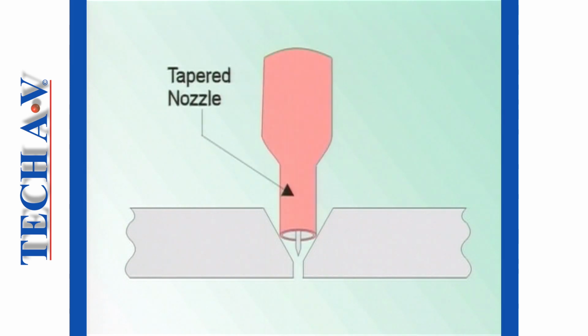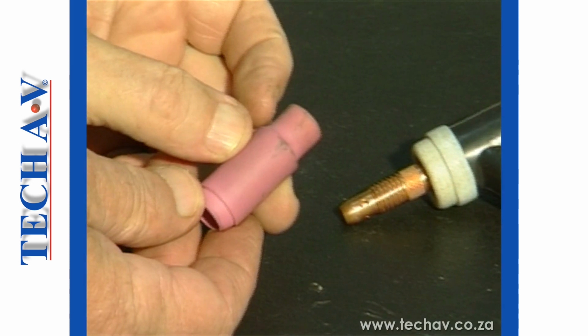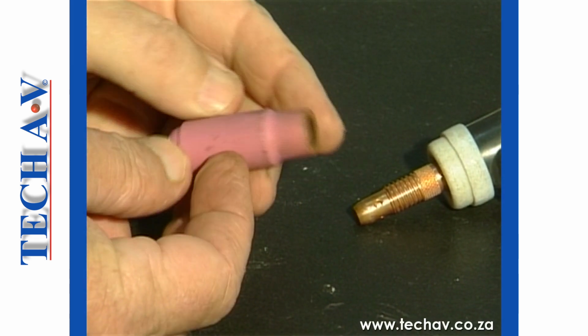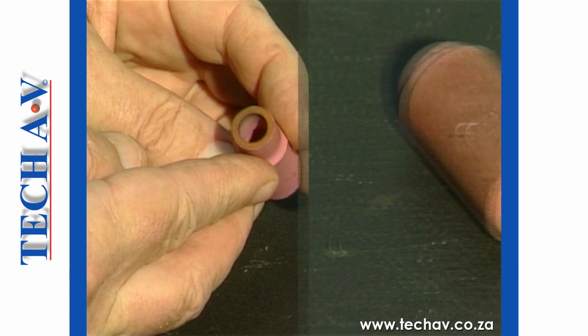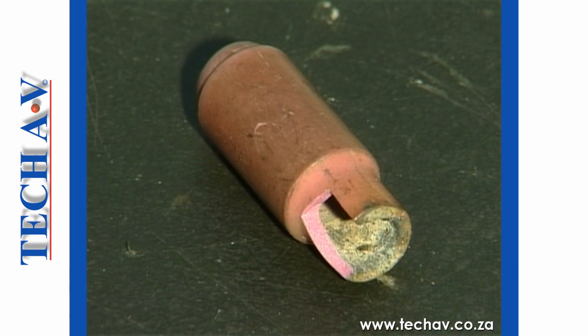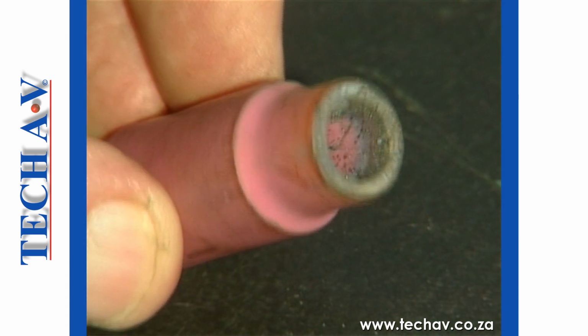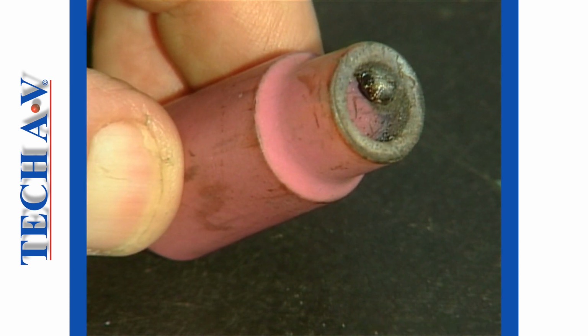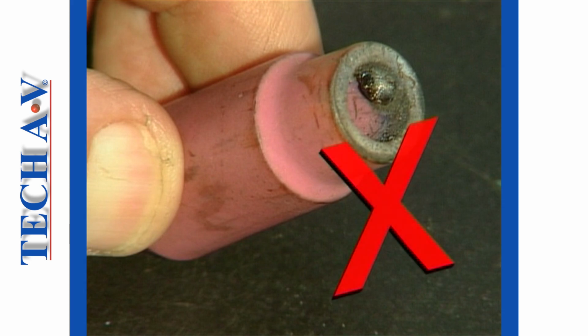For example, when making a root run in a deep groove, a tapered nozzle needs to be used. Before fitting a nozzle, inspect it for damage. Damage such as this renders the nozzle totally useless, as gas will escape and the weld will not be shielded. In this example, there is metal spatter deposited inside the opening caused from overheating. This too renders a nozzle unsuitable for use because the flow of gas will not be evenly spread.